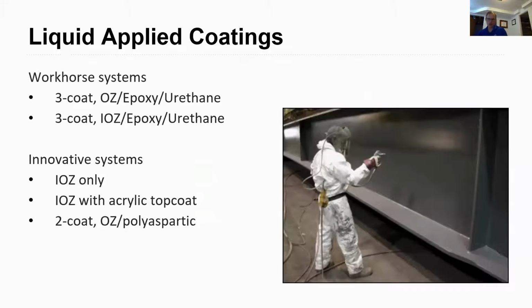I mentioned that the workhorse systems are the 3-coat systems, and they definitely are, but there are some newer systems that are available as well. So a single IOZ coat, that's something that we're currently researching. There's also some 2-coat systems that are made up of IOZ as the base layer and then an acrylic top coat. Then there's also one that uses an organic zinc primer and a polyaspartic top coat. The organic zinc primer is supposedly easier to apply, and it cures a lot more consistently than an IOZ primer does. So that's gaining some popularity, especially in the Northeast.